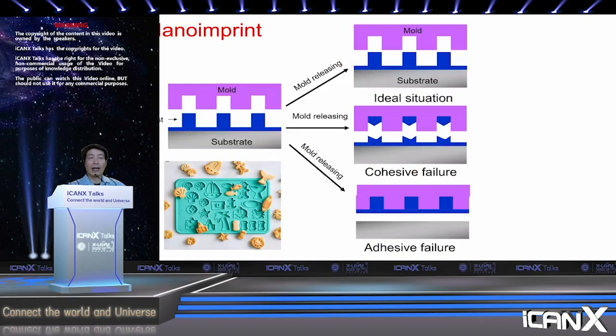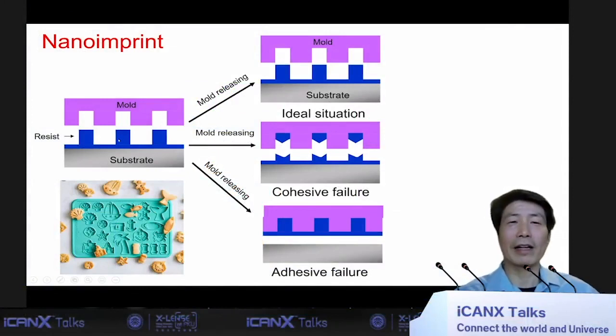It's an analogy of how you make cookies out of a mold. But in this case, the mold basically is shrunk down to nanoscale dimensions. But otherwise, it's very similar. You can take any plastic, a thermoplastic for example, heat it up above its glass transition temperature when it's soft, and you can emboss your pattern into it. This is entirely conformal. As long as you are able to make your mold, you can potentially replicate. Imprinting is very easy. You can push into any material. You can use UV curable material, where you use light to cure it.